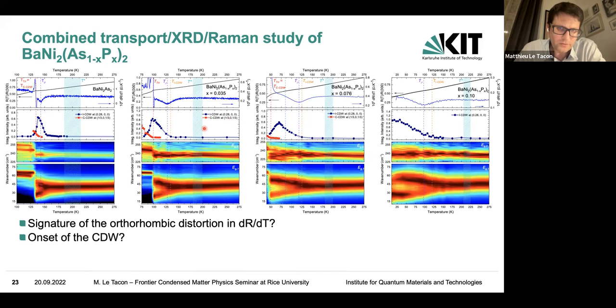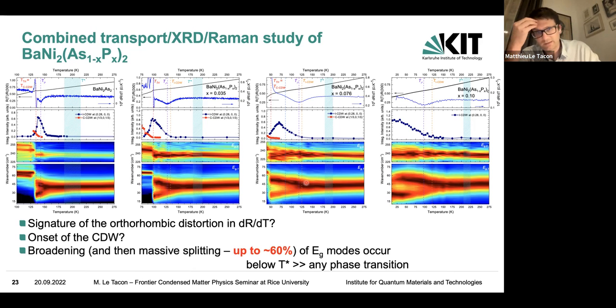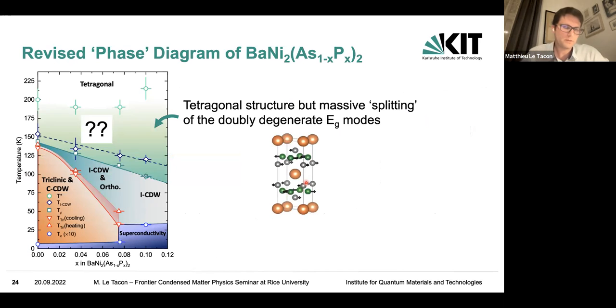And again, if we try to compare that with the different phase, for instance with the onset of the CDW, it's a bit disturbing, because if you look carefully, the mode splits, but the mode is very broad to start with. I mentioned it starts to soften upon cooling, and then it broadens and splits. So the onset of the splitting can be seen with the beginning of the broadening of the line. And that broadening is occurring at very high temperature, much higher than where we can detect, for instance, the CDW satellite, at least with an X-ray tube. So this has been extremely puzzling. We measured the whole series, and then we put this into a diagram, and that's what we found.